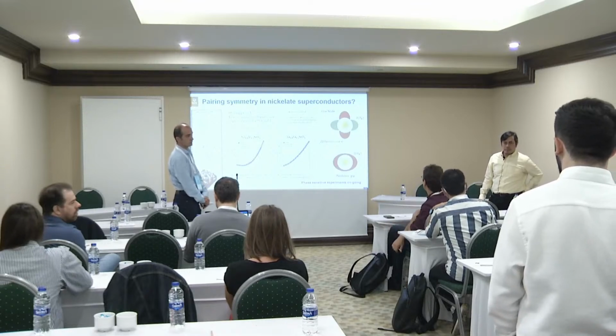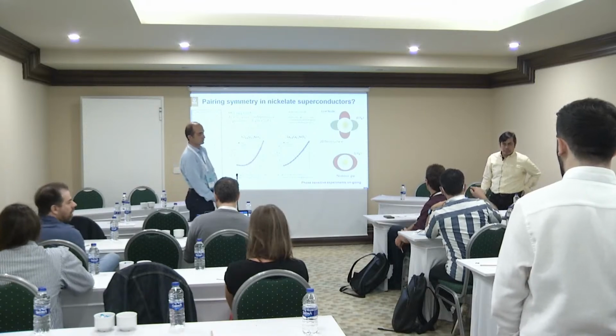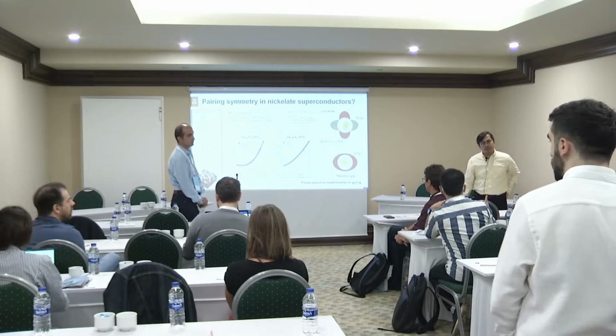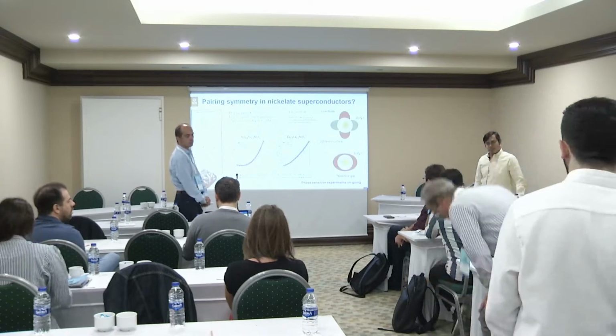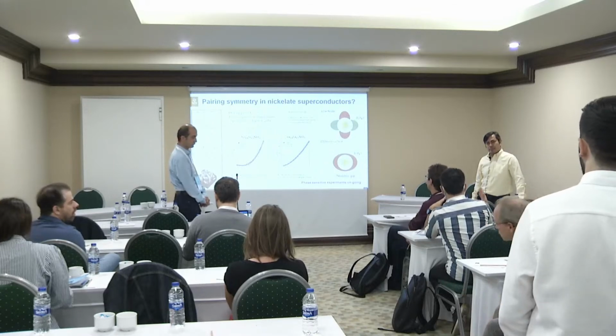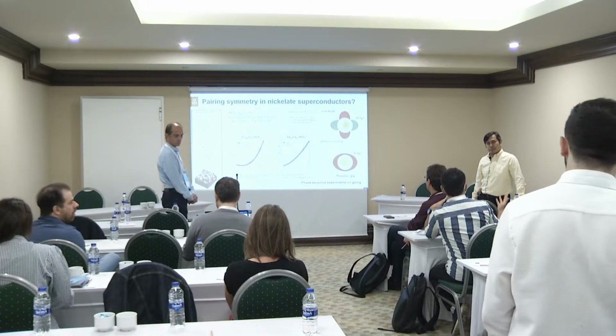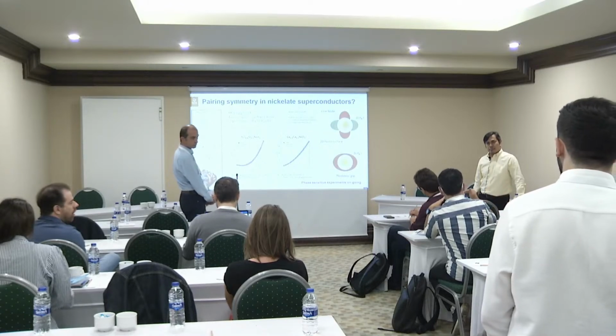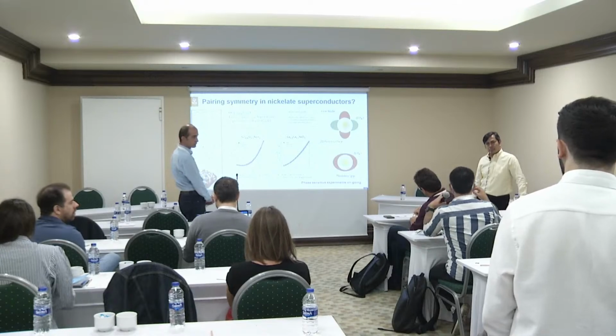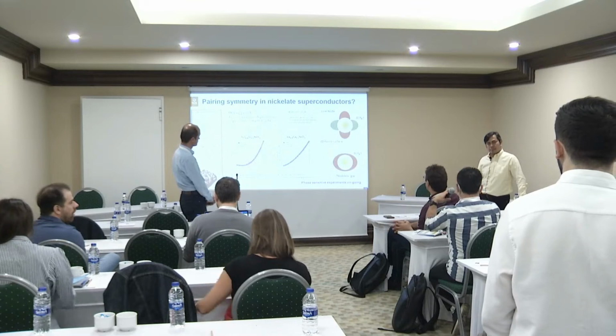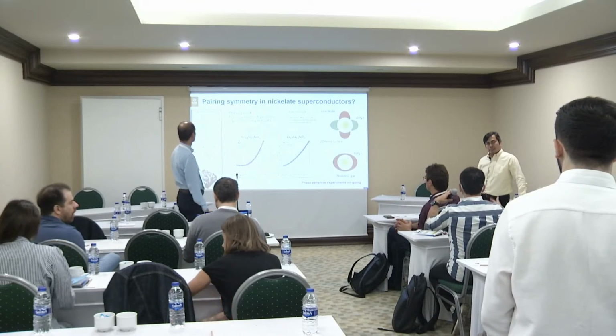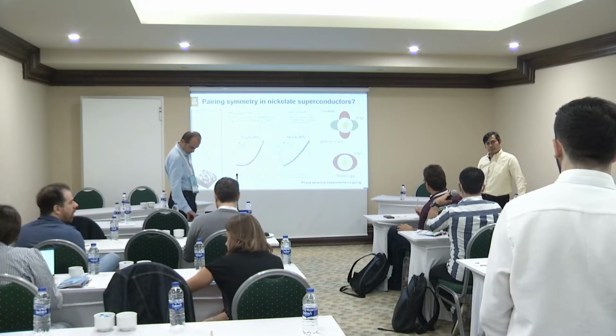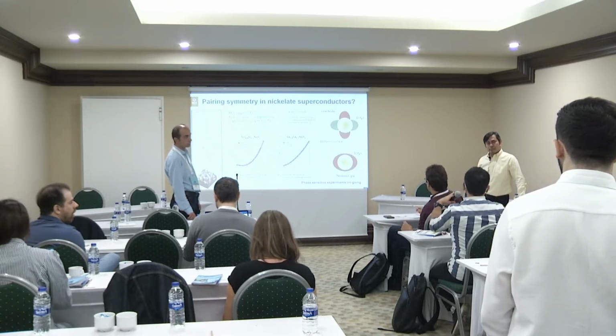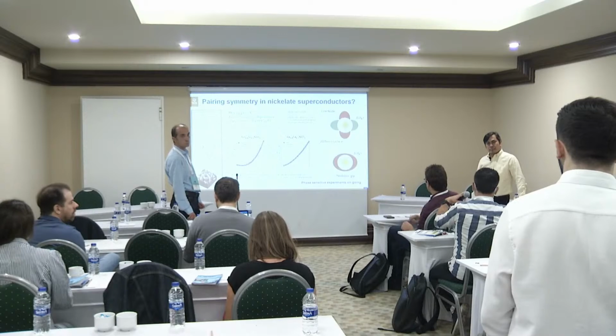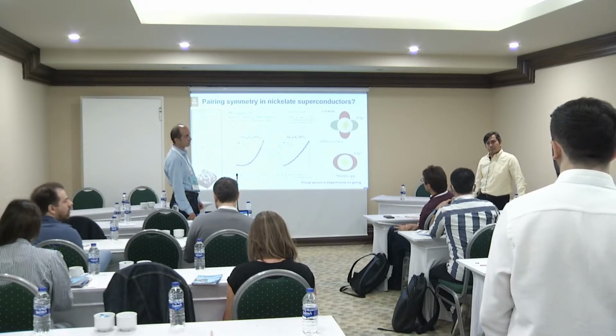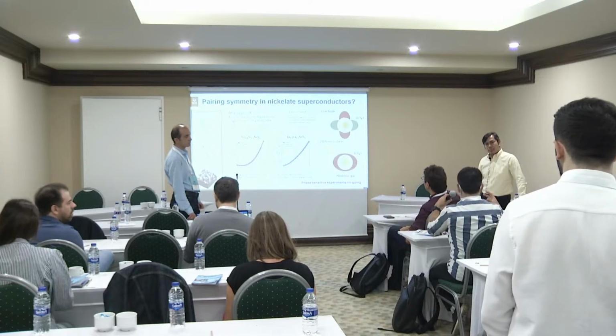My question is about the phase diagram. You have a phase diagram with a dome shape. You have two hills, because of the transition from electron doped to hole doped. What I expect, if it's similar to cuprate, is that there should be some separation, and at low doping, compensation of the carrier concentration, and then I expected it to drop down in Tc, and then to see some kind of pseudogap or some kind of correlation effect, and then again the hole-doped regime, then we can see another dome shaped phase diagram. Can you explain why you have this kind of combined phase transition?